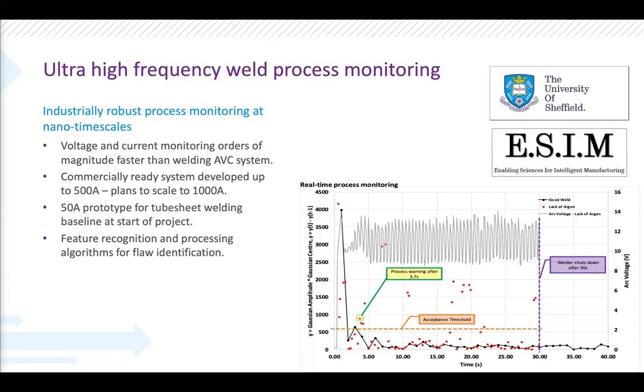But the system developed by the physics department was working on an order of magnitude of about 100 times faster than this current system. So this is looking for high frequency fluctuations and disturbances in the welding process and correlating that to welding flaws to enable us to flag conditions as they occur in process. They previously had a proof of concept system that had been established on tube sheet welding, rated to 50 amps. So their work was a lot of hardware development and scaling this up to be rated for the industrial scale, going up to a 500 amp system initially and ready to go up to 1000 amp, and then establishing the methods by which they can train their system and do the signal processing to find these flaws as we start moving towards industrial applications where we start simulating the conditions and flaws as they're deposited. Next slide.